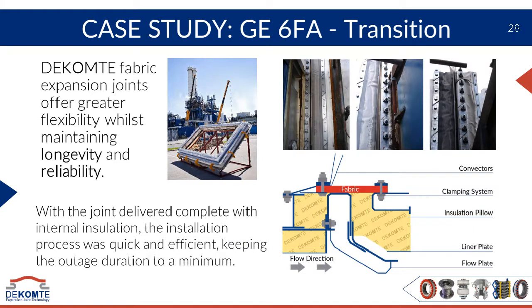Another solution on GT exhaust is just to touch on a hot to cold transition, because in most gas turbine exhaust systems it's the expansion joint which makes that migration from the gas turbine exhaust diffuser, which is externally insulated, and the boiler side, which is internally insulated. And so there we need a different type of expansion joint system where on the inlet frame, we address the steel frame issues of fatigue, stress and temperature gradients, and on the outlet side, we address the issues of insulation integration and liner plate integration. On the outlet side, where there's internal insulation and liner plates, very often the problems are caused by just too many interfaces at the same location as the flange, as the expansion joint frame. And so integrating that adjacent part is the key to ensuring maximum life of the expansion joint.